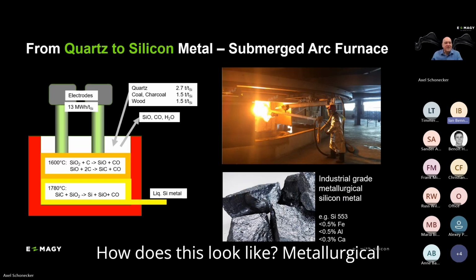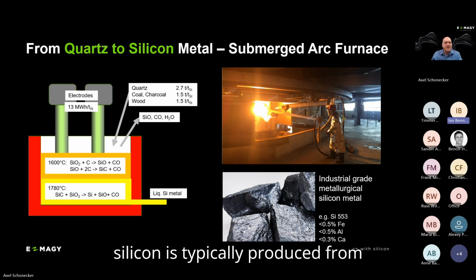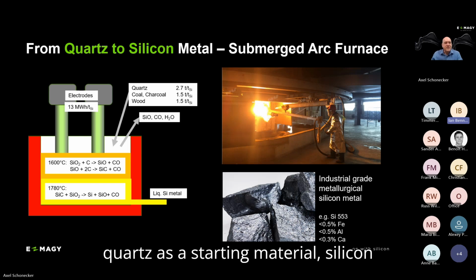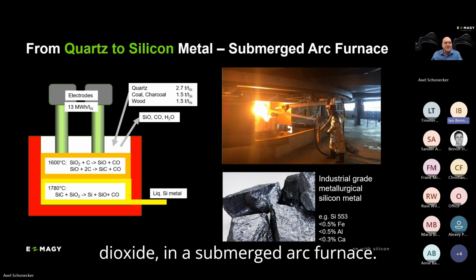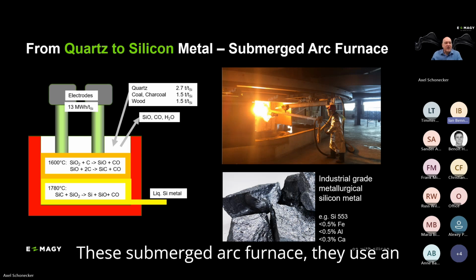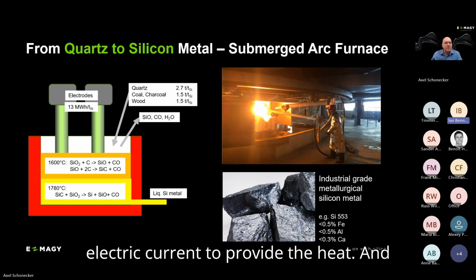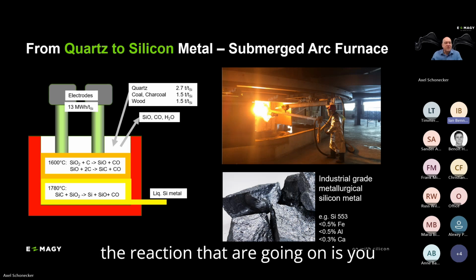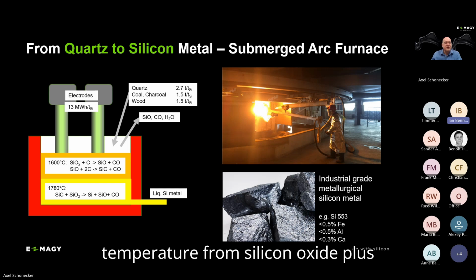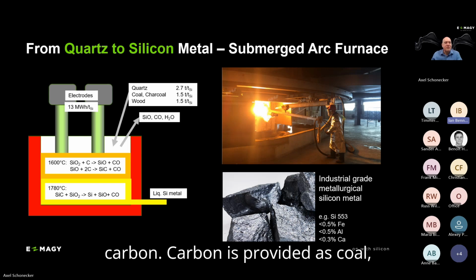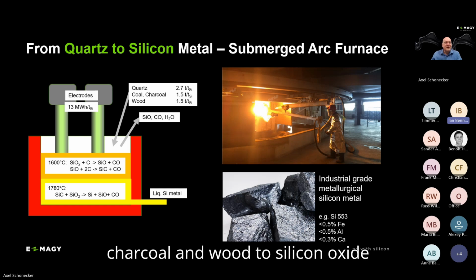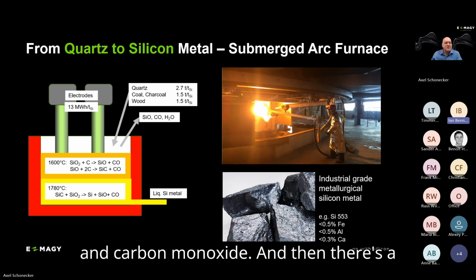How does this look like? Metallurgical silicon is typically produced from quartz as a starting material, silicon dioxide, in a submerged arc furnace. These submerged arc furnaces use an electric current to provide the heat. And the reaction that is going on is, at a little bit lower temperature, silicon dioxide plus carbon, where carbon is provided as coal, charcoal, and wood, giving silicon oxide and carbon monoxide.